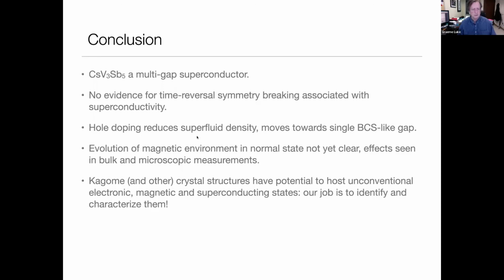Just to conclude, where we are right now is very much a work in progress. All of this work is unpublished. We'll hopefully be completing the manuscript shortly. We've discovered that this material is a multi-gap superconductor, possibly with changes in the gap symmetry as we change the doping in it. We don't see any evidence for broken time reversal symmetry associated with superconductivity, although we do see some magnetic environment changes in the normal state.